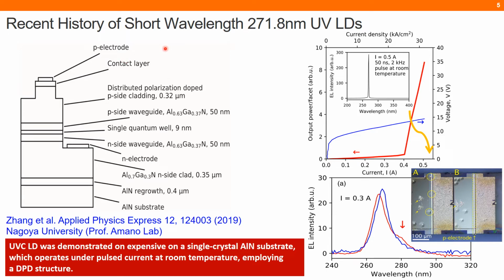Here I would present the short history of the short wavelength 271 nanometer UV laser diode, which was demonstrated by Professor Amano's group at Nagoya University. They grew the device structure on an aluminum nitride single crystal substrate, which is quite expensive.